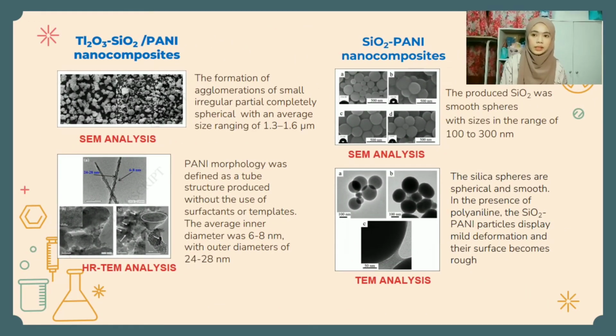For the same analysis of titanium oxide silica polyaniline nanocomposite, there was formation of agglomerations of small irregular, completely spherical particles with an average size ranging from 1.3 to 1.6 micrometer. For the high resolution TEM analysis, the morphology was defined as a tube structure produced without the use of surfactant or templates. The average inner diameter was 6 to 8 nanometer with the outer diameter of 24 to 28 nanometer.